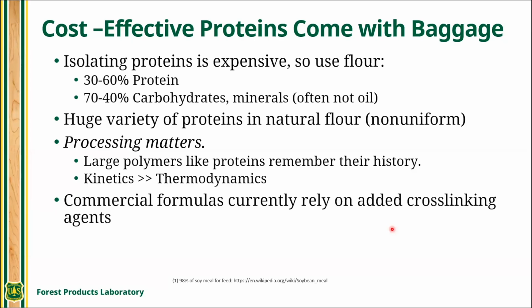Another thing about working with proteins is that they're really big polymers. And because they're such big polymers, kinetics very much limits their reorientation, and they're very sticky also. So because of that, they do not go to their thermodynamic minimum in any reasonable time frame under most conditions, and therefore their history matters. You take your urea formaldehyde, and it doesn't matter if it was 60 degrees half an hour ago and you cooled it down, or whatever. Its history doesn't matter as far as the conformation of the molecule. But with these large molecules, it's big. So history matters. And therefore, in papers, I always look for what exact grade and style of protein did you get? What was the processing history of that protein? Because it'll affect your results.